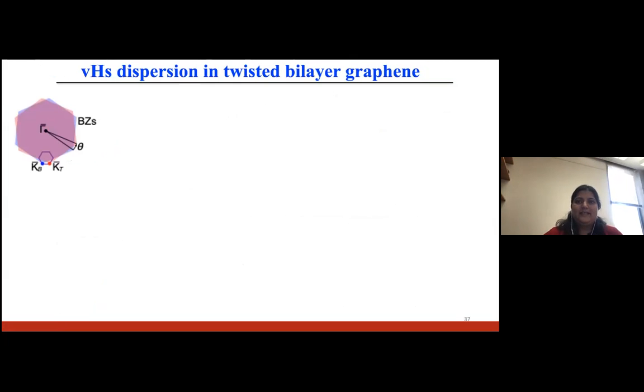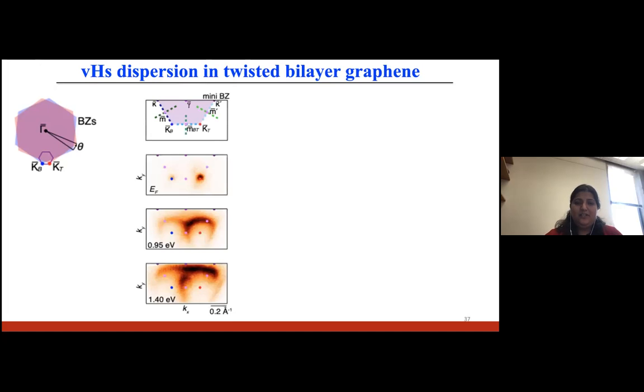Okay, so next, look at the mini Brillouin zone, and that is what I'm showing here. And here are the constant energy cuts of this mini Brillouin zone, and I'm labeling the high symmetry points with these colored dots. So if the K of the top graphene has a blue dot, correspondingly this K point of the bottom graphene is here, and this is denoted by this blue dot. And so as you can see,